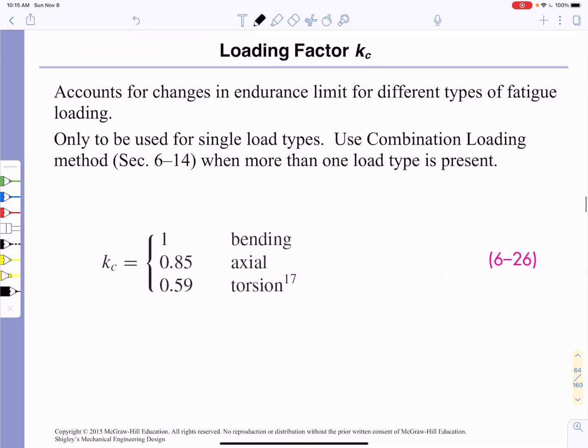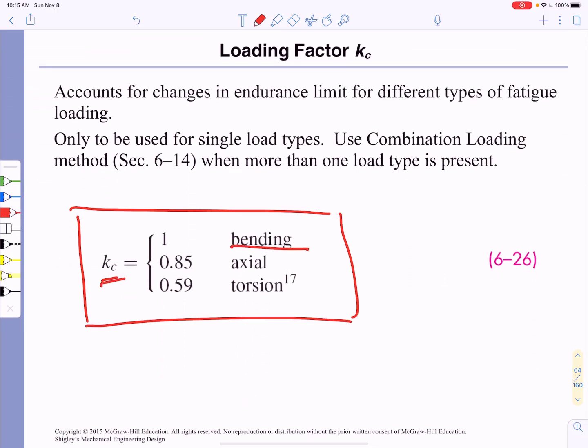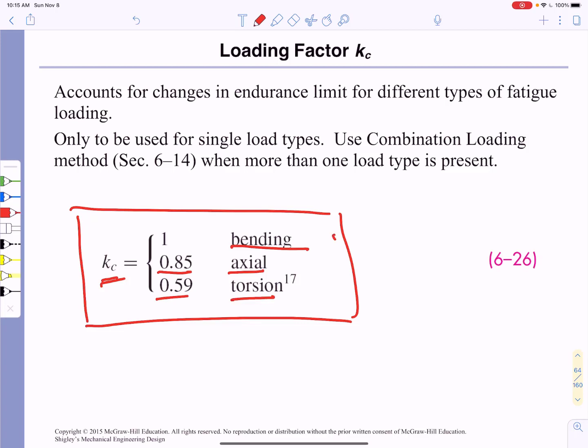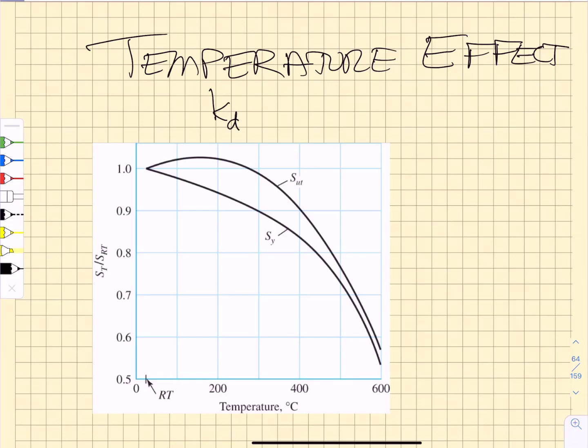The loading factor modifications are shown in equation 626, where we do no modification if it's in bending — that's what we develop all of this fatigue analysis from, bending loads. If you move to axial loads, you multiply by a factor of 0.85 because you have to knock down the endurance limit, and you knock it down even more. Keep in mind, this is pure bending, pure axial loading, and pure torsion. When we developed our understanding of endurance strength, it was all tabulated for fully reversed bending at room temperature on polished specimens.